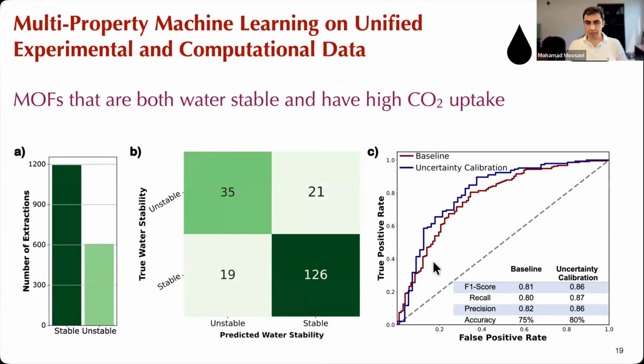Another useful thing we can do when we have unified such a data set is property prediction with machine learning from experimental data and computational data. For example, if you want to design materials for carbon capture, for CO2 uptake, usually we can predict the CO2 uptake by computational chemistry. We can run GCMC simulation and calculate the uptake. The water stability, on the other hand, is not something easy to compute. So what we can do instead is to collect data from the literature. That's part of the MOF community effort, where we collected all this data from literature. People report water stability, and then we can use those labels to train a machine learning model. This shows that, in fact, we can get a good prediction. Predicting water stability is possible with these models, and it reaches a good accuracy.